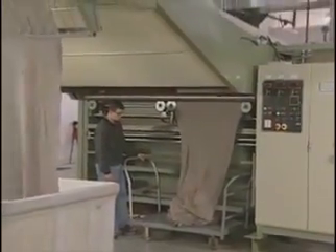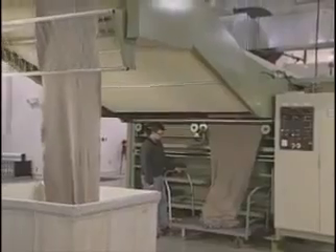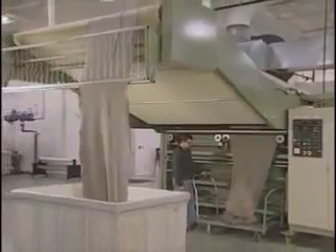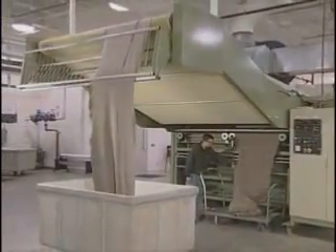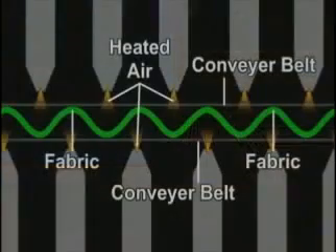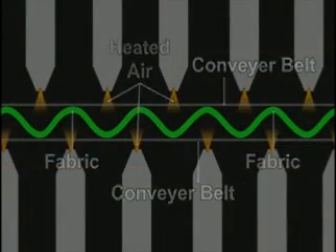The methods used to shrink the fabric must be able to overcome the static friction that exists within the knitted structure. Key factors for relaxation drying should include: 1. Releasing of all tensions from the fabric. 2. The use of softeners to aid fabric structure mobility by reducing the static friction at yarn intersections. 3. Sufficient and uniform mechanical action to overpower all static friction within the structure, but at levels low enough to prevent stretching. 4. Mechanical action by airflow and belt vibration.